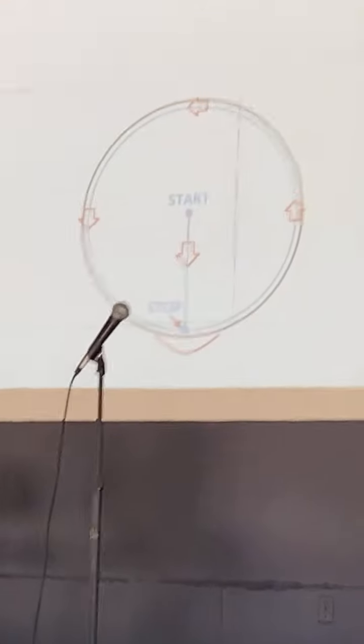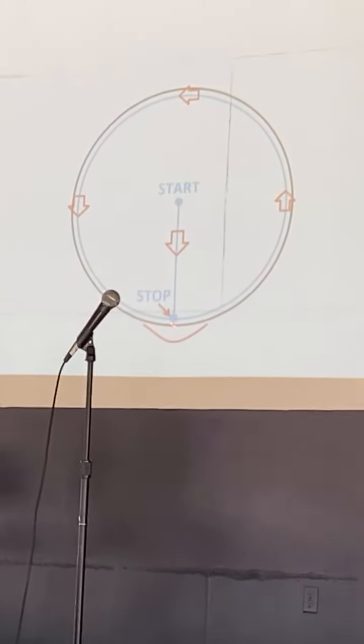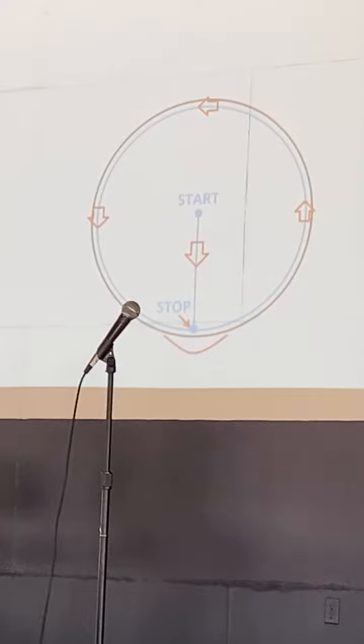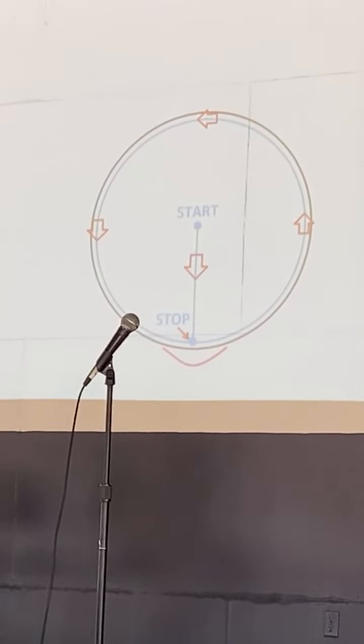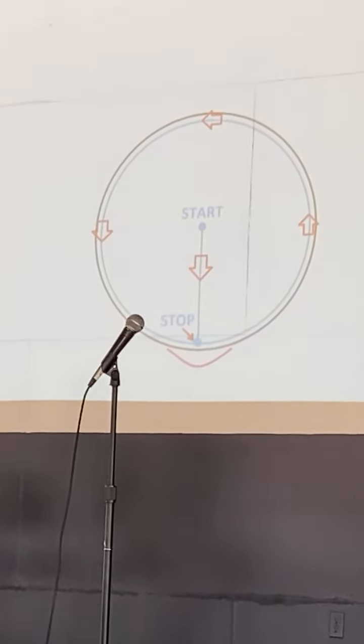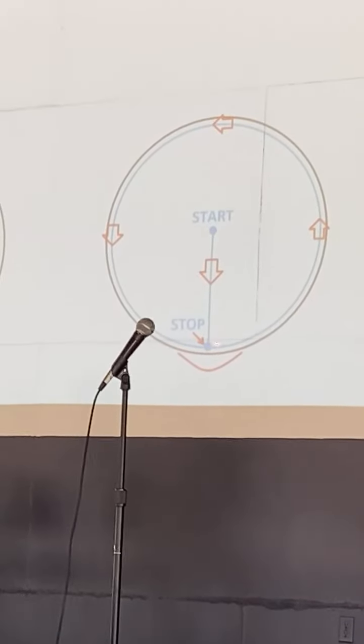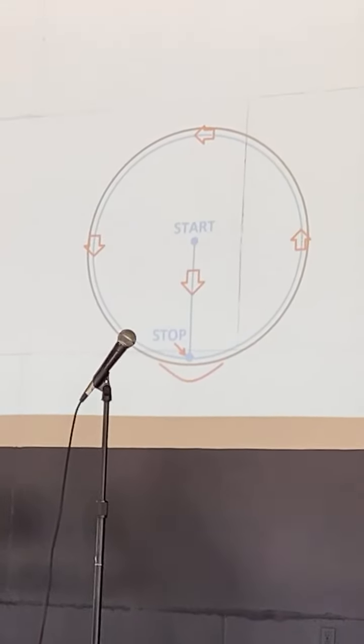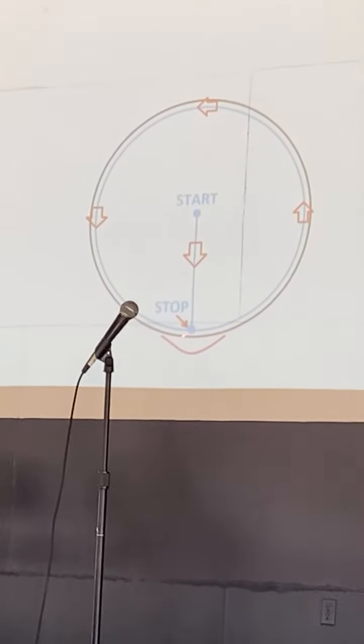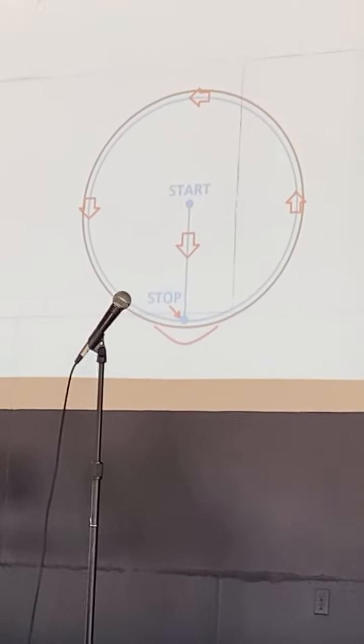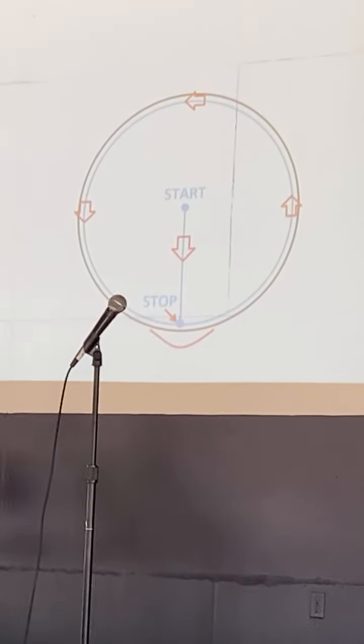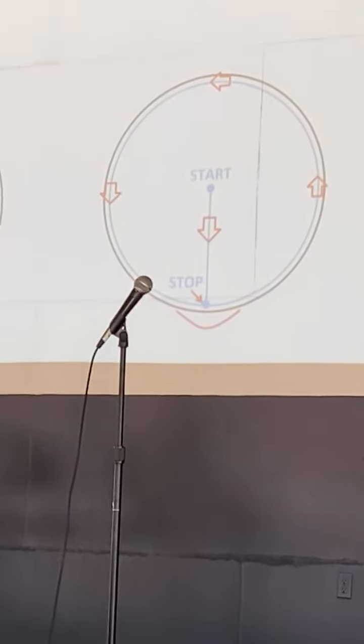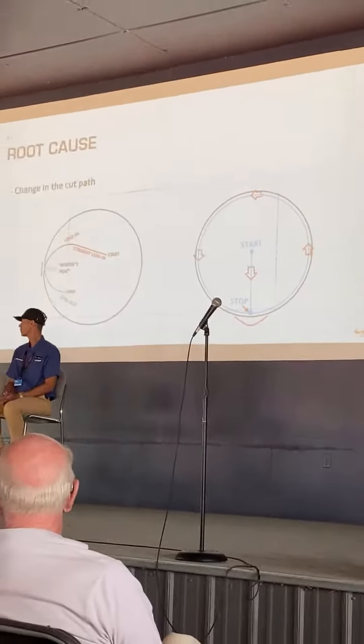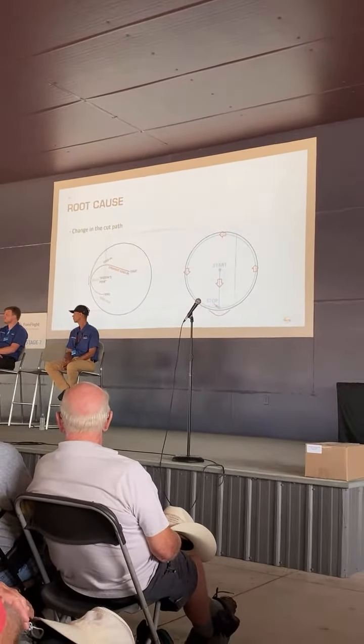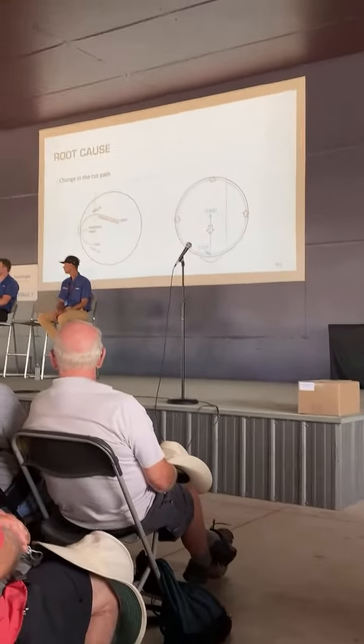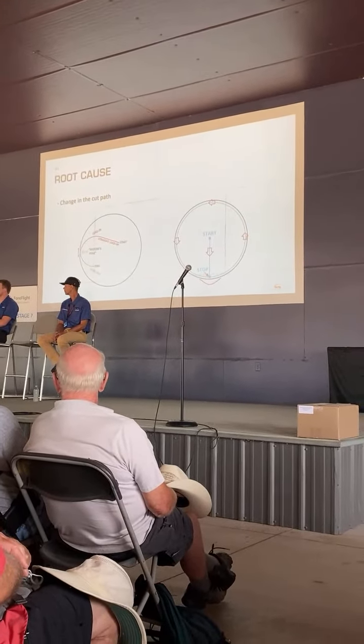Over here on the right, you have the start button in the center, it moves down, and the laser, what was actually happening from our laser cut vendor is they started in the center, they came down to the bottom. The laser has to pause for a very short time as it changes direction, goes around the part, and then stops in the same location. Another thing we discovered is every PO that we were sending over to these laser manufacturers, they were reprogramming every time. So what we thought we had settled out at the beginning of the process was changing over time.